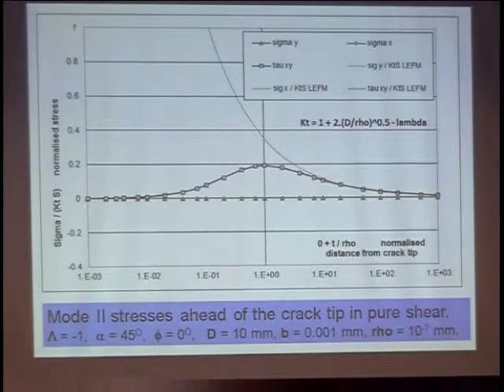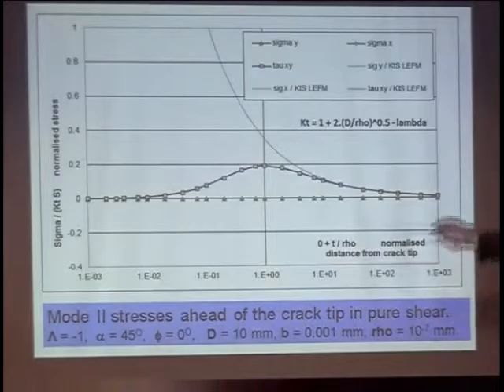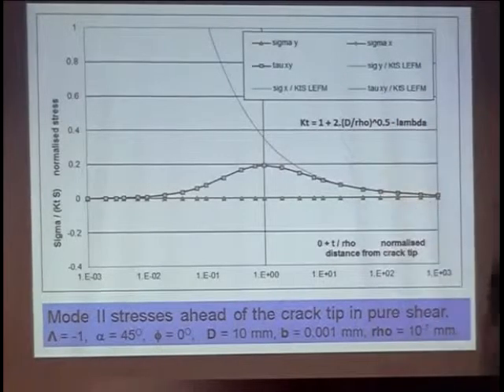Well, actually this tells you why the Sheffield tests failed. So we should have actually thought more about this picture. The idea in mode 2 was to suppress the mode 1 cracks. Mode 2 crack will initiate at the notch root, which is over here. And guess what? There's no shear stress. And there's no sigma x, there's no sigma y.